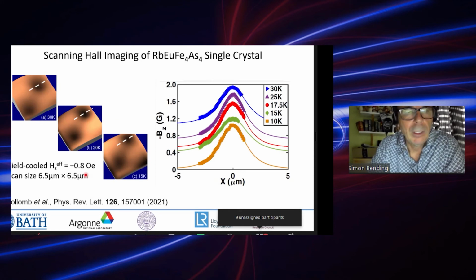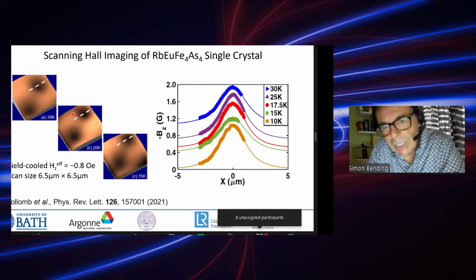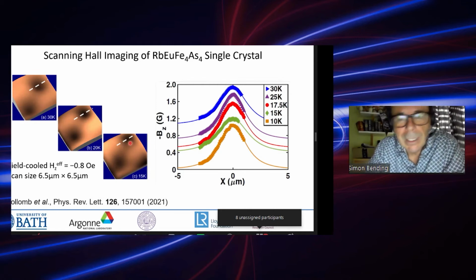This is a much smaller field of view of about 6.5 by 6.5 microns. And if you look very carefully at these images, this is at 30 Kelvin, this is at 20 Kelvin, this is at 15 Kelvin, you can just about discern, if you look with lover's eyes like I can, that actually the vortices broaden here as you go down to 15 Kelvin. Initially they shrink a little bit and then they broaden.